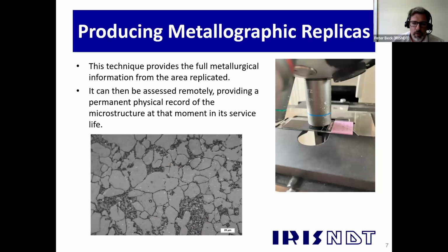So this is the kind of thing that we can see from a replica. We would typically look at replicas using magnifications between about 50 and 500 times. The image you can see there at the bottom is taken at 500 times magnification. That's pretty similar to if we looked at an actual metal surface. We do get some imperfections from this technique. Mainly you can see this white speckled appearance in some of the pearlite regions, and that's an artifact of the technique itself.